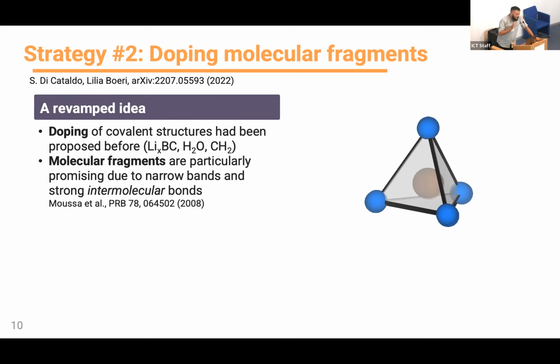Now, what's quite special about molecular fragments is that they are characterized by very narrow electronic bands, so a very sharp density of states. And the intramolecular bonds are typically very strong. There is very nice work from Moussa and Cohen from 2008 in which they really examine the electron-phonon coupling of different molecular fragments to hypothetically see if they could be good superconductors.